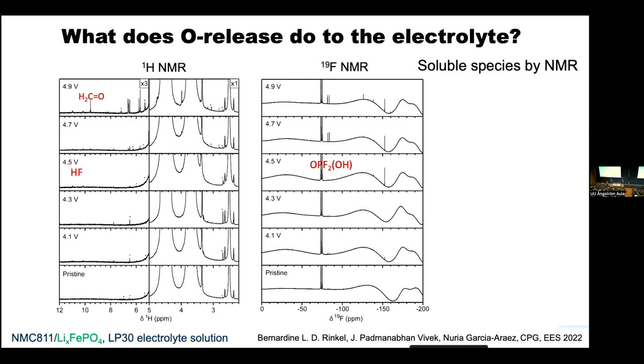So then what happens to this oxygen? My former student Didi did a very detailed analysis with our favorite technique, NMR, to look at all of the gory degradation products that are formed. I'm not going to go through all of this because it's really less inspirational to look at NMR peaks, but the bottom line is that there are two processes. Above 4.3 volts, you start to see CO2, CO, and oxygen evolution, which then creates a whole series of new degradation processes. Below 4.3 volts, you just see degradation to form HF.